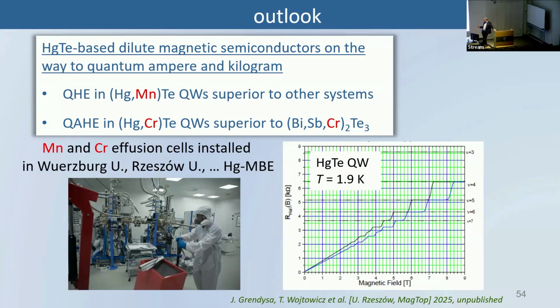And the samples are macroscopic, a few millimeters. So we do not expect the quantum spin Hall effect. The resistance of the channels will be very large, yeah, because the samples are macroscopic. And of course, this is not as interesting. What we look for are samples with manganese or chromium, which should show a very good quantum Hall effect in the case of manganese and a very good quantum anomalous Hall effect in the case of chromium.